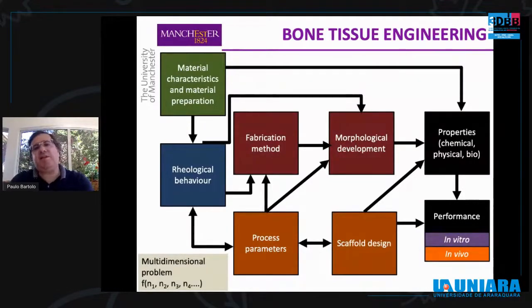As I mentioned along this presentation, one of our aims is to design and develop structures with optimized properties. This is very complex because, for example, if you change the material preparation method, you change the rheological behavior of the material, and then we need to adjust the processing parameters. By changing the processing parameters, this has an impact on the scaffold design and an impact on the morphological development. And as a consequence, we are changing the chemical, physical, bio properties of the final scaffolds. So we need to understand and to establish models correlating all of these effects. And this is really complex.